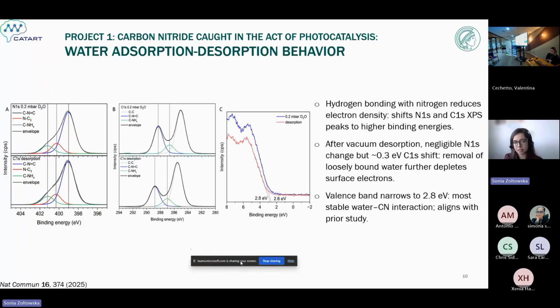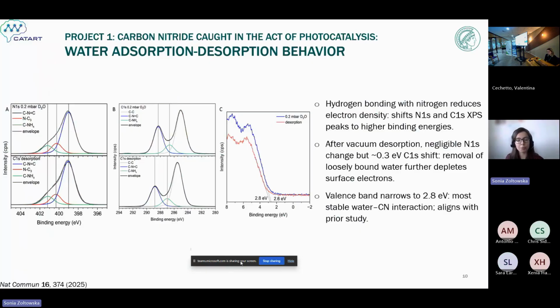However, in the study of the entire catalytic process, an important question arose: will it be possible to get the carbon nitride back to its original properties? So if we desorb the water, will we be able to obtain the same electronic signature? And this is what we did. We performed the desorption by simply evacuating the measurement cell to ultra-high vacuum conditions, and we kept the sample there for approximately 1 hour. And after that, we measured the XPS spectrum again.